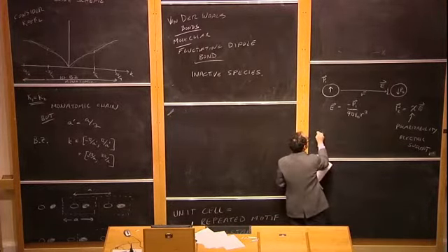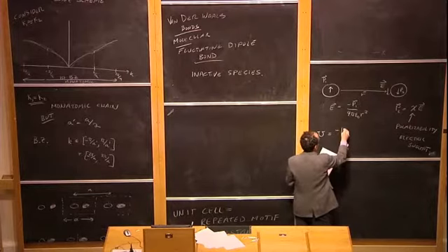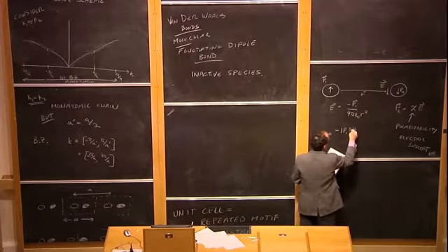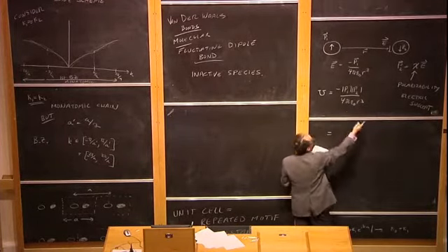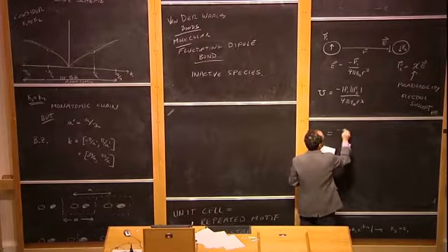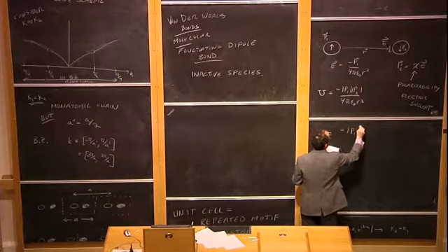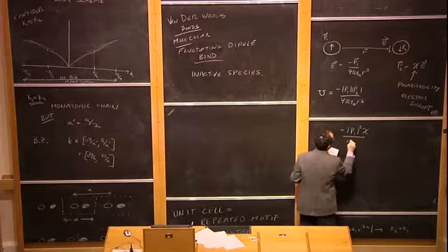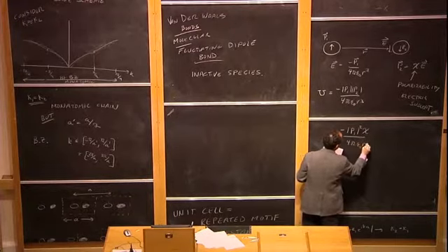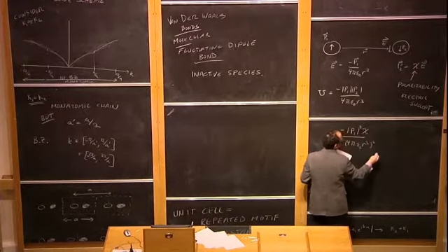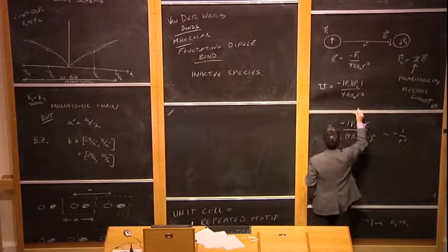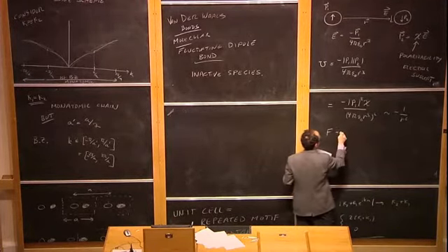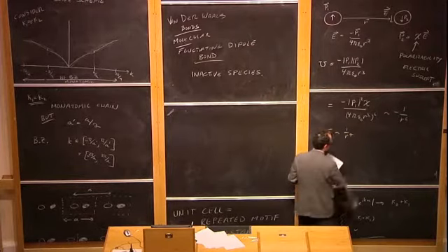And you'll remember that the energy of two dipole moments is minus P1 P2 over 4 pi epsilon naught r cubed. So the total energy is then, just plugging these things all together, minus P1 squared chi over (4 pi epsilon naught r cubed) all squared. And in particular, this is negative and goes as 1 over r to the 6th. So the force goes as 1 over r to the 7th.